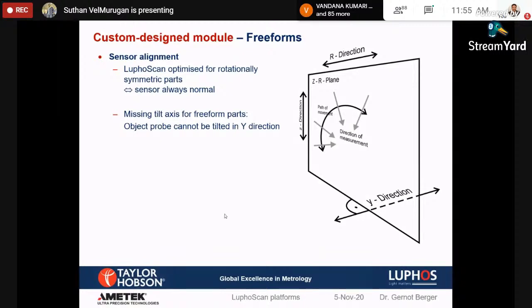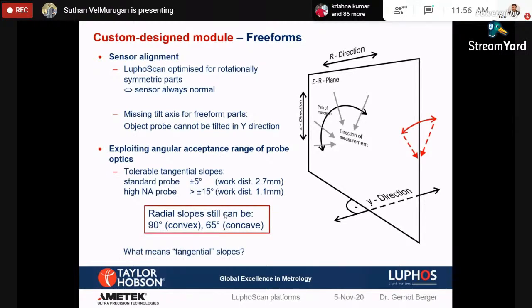Any of the LuphoScan machines can measure whichever I showed. But we have some peculiar examples of the free-form sample. Free-form, as I said, can be anything. It can be a customer-specific requirement of angle. So we can generate or make specific software for the free-form measurement, and we can make a special probe for the free-form measurement. There are custom-specific modules available that can be offered to any customer based on the free-form requirement. Mainly, if the free-form slope is plus or minus 5 degrees,